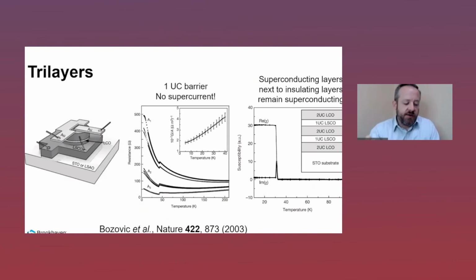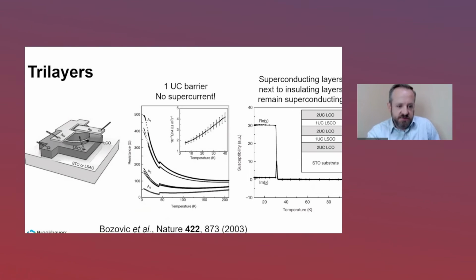Some early work by Bozovic and others on superconductor-insulator-superconductor sandwich type junctions showed some very interesting and important results. The structure of their devices is shown there on the left, which consists of optimally doped lanthanum strontium copper oxide layers separated by a single unit cell of insulating lanthanum copper oxide. What was observed is that although the barrier is extremely thin, it prevented any supercurrent from flowing from one side of the junction to the other. And just to be clear, this is in the c-axis.